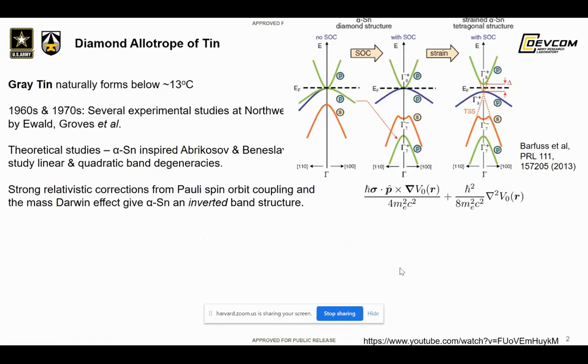And you can see it has all the characteristics of a topological insulator, if you can split this degeneracy point here. With strain, you can achieve that, as will be discussed in the rest of the talk. So basically it has that interesting characteristic in that it has degeneracy of the gamma 8 conduction and valence band, and the possibility of getting an inverted band structure with the gamma 7 band being below, which is typically the electron band being below the valence band.